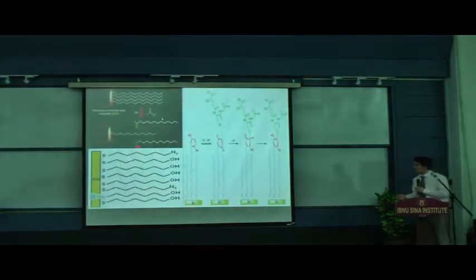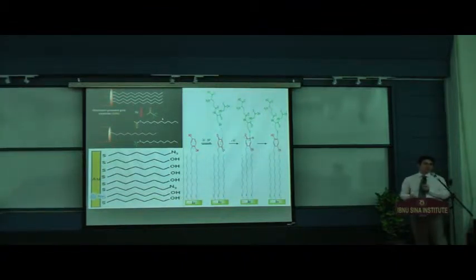here, next one, here. Having these all together, we also try to investigate this chemistry at the surface of two-dimensional gold, let's say gold electrode, which is self-assembled monolayer technique. So we made self-assembled monolayer technique and we did the same chemistry and we saw same release.